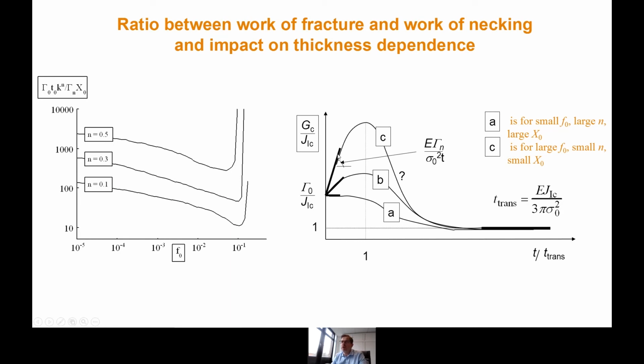And that explains why people sometimes find that the fracture toughness first increases a lot with thickness, reaches a maximum, then decreases to an even lower value. But sometimes you may be in regimes where the work of necking is insignificant, and then you can have your fracture toughness decreasing down to plane strain. And this is still open for discussion for sure. I hope that by giving you this extra information, that helps understanding better what is behind the essential work of fracture.